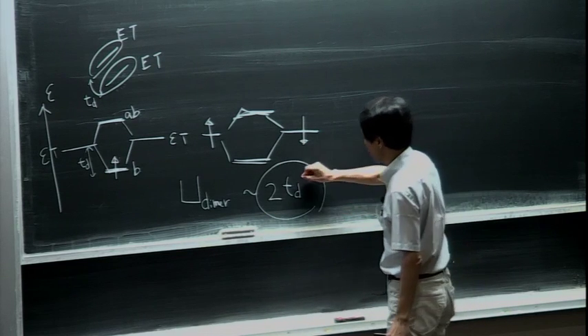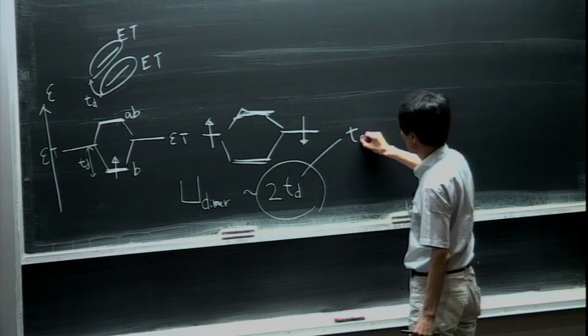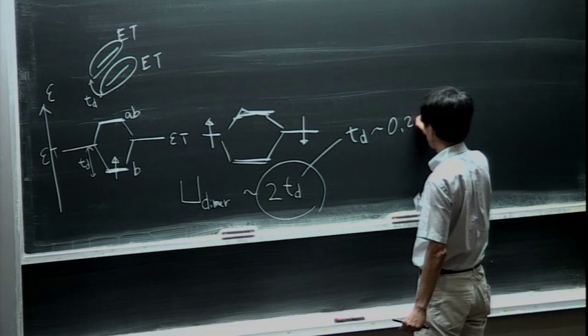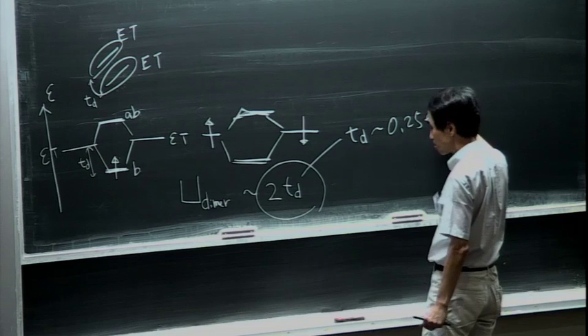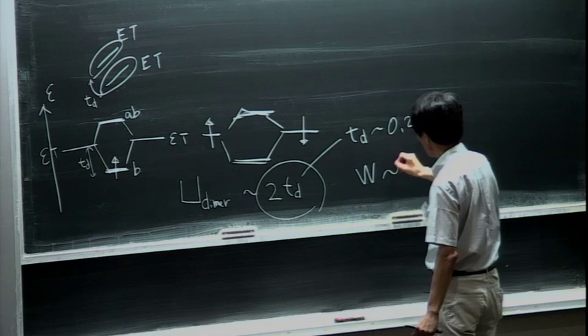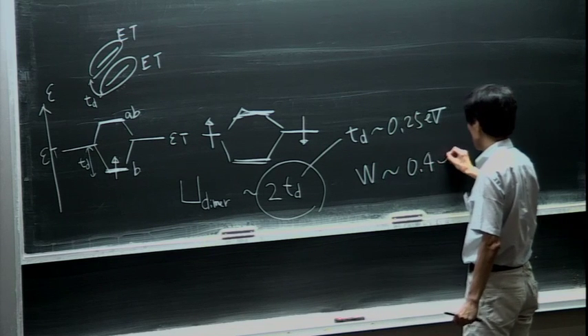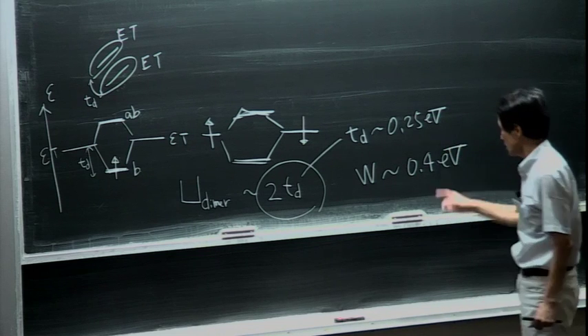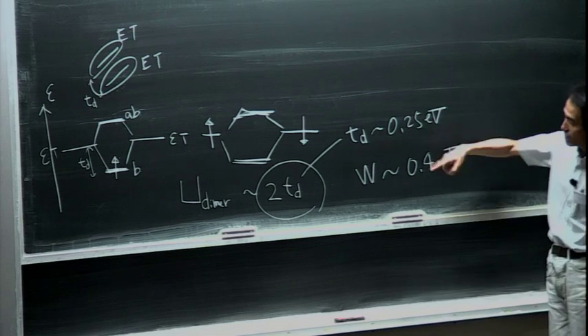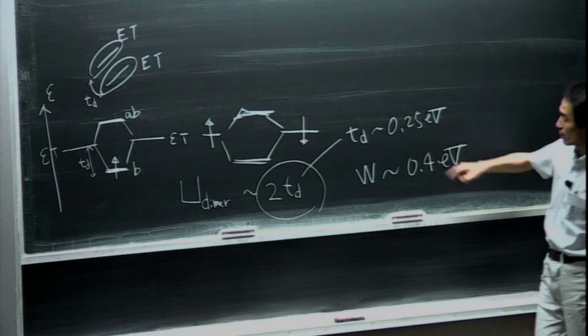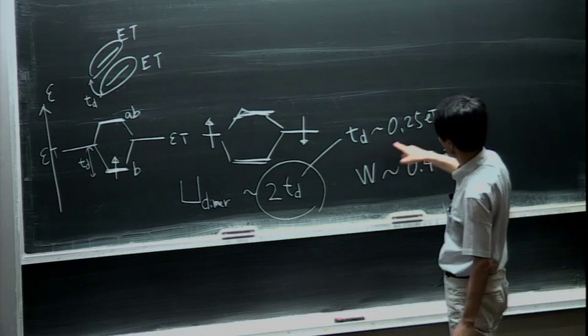From the band structure calculations, TD is 0.25 electron volts, and the band structure gives 0.4 electron volts—so it's comparable. Twice of TD is 0.5.